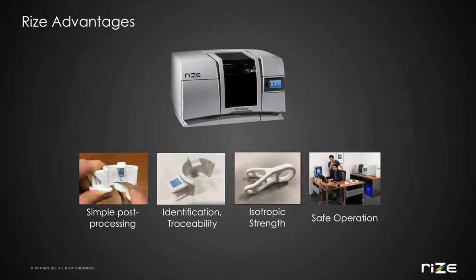There are unique advantages to this process. First, jetting the release agent between the support structures and part enables very simple post-processing. The part can be peeled away from the support structures without chemicals, without additional equipment, very quickly, leaving a smooth surface finish. Secondly, the marking inks let you apply text and graphics to the part for identification, tracing information, usage instructions, or safety information. This marking capability adds a whole new dimension of functionality to the part. And in developing a polymer to complement the process, we designed a material that provides isotropic strength so you don't have to design your part to compensate for weak interlayer bonding. On safety, we used medical grade components that don't leach, contaminate, or emit VOCs during the print process.